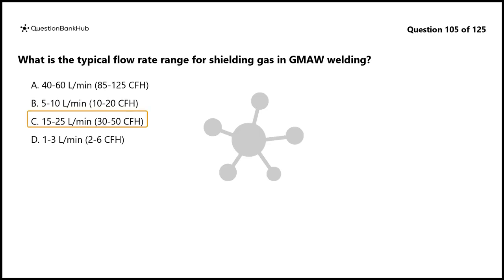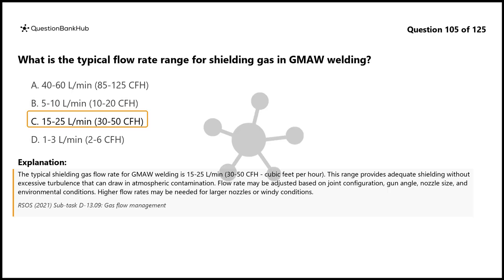The correct answer is C. 15 to 25 liters per minute, 30 to 50 cubic feet per hour. The typical shielding gas flow rate for GMAW welding is 15 to 25 liters per minute, 30 to 50 cubic feet per hour. This range provides adequate shielding without excessive turbulence that can draw in atmospheric contamination. Flow rate may be adjusted based on joint configuration, gun angle, nozzle size, and environmental conditions. Higher flow rates may be needed for larger nozzles or windy conditions.